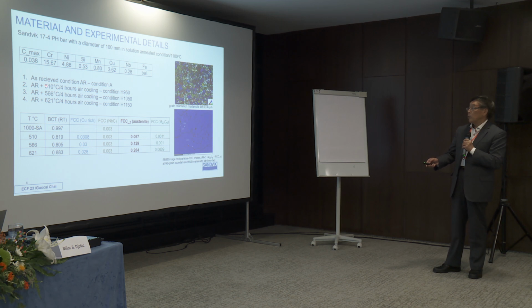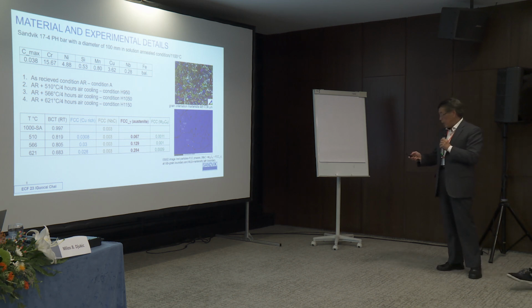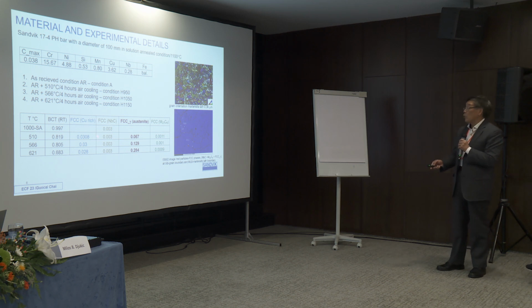510, 566, and 621. So why do we choose these temperatures? This is according to the American definition, this type of number here. After that we check the microstructure. Here, the as-received is mainly martensitic with some niobium carbides. After tempering, we found three new phases. One is a copper-rich phase, but the influence of temperature is very small.